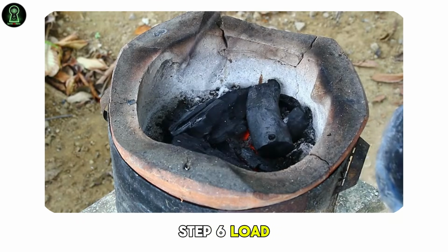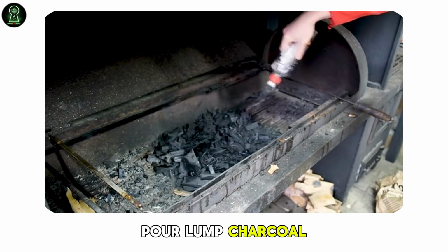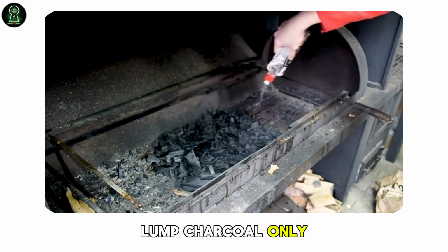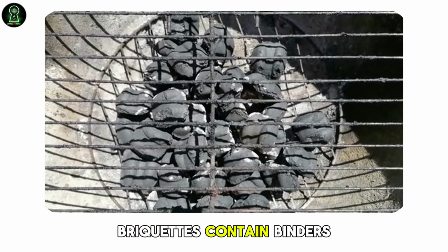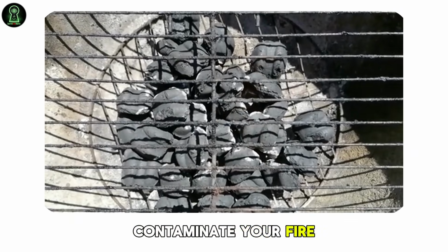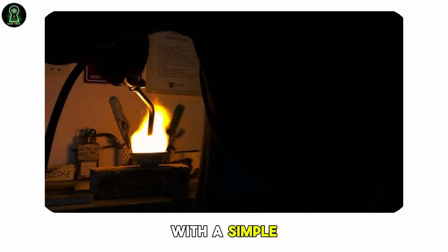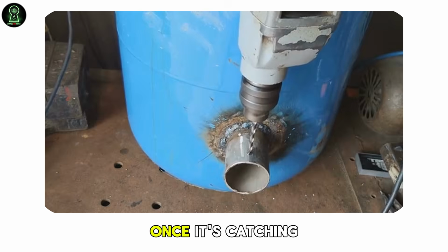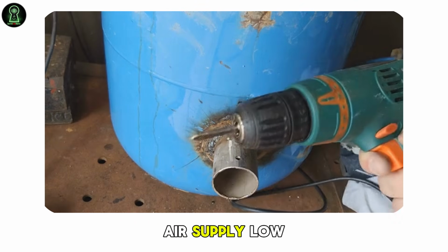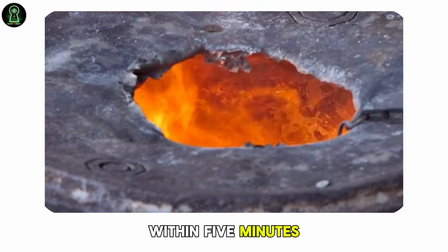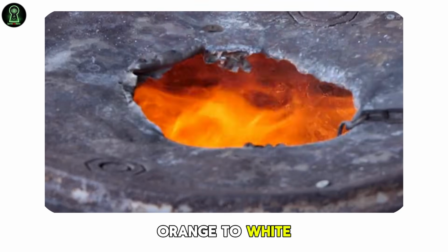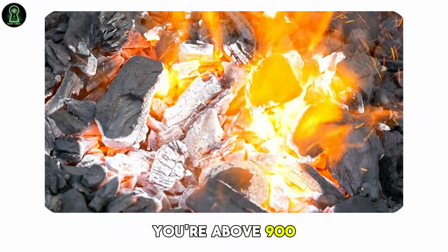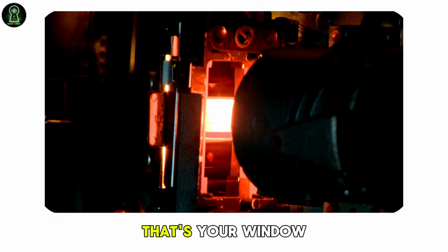Step 6, load and light. Pour lump charcoal into the fire bowl. Lump charcoal only, not briquettes. Briquettes contain binders and additives that contaminate your fire and your metal. Light the charcoal with a simple lighter and a piece of paper. Once it's catching, turn on your air supply. Low to start. Within 5 minutes, you'll see the charcoal turn from orange to white. White charcoal means you're above 900 degrees Celsius. That's your forge, that's your window.